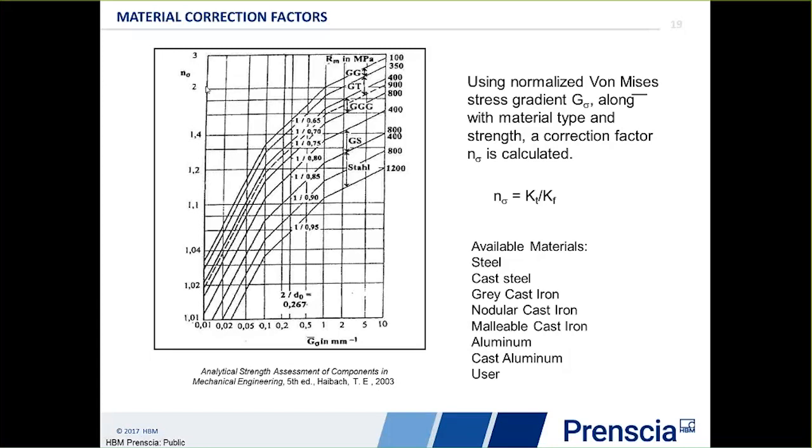And you'll see, especially for gray cast iron, that these corrections are relatively high. So basically, I'm cutting my stress level, in this case, by a factor of 2, that we use for my fatigue calculation. If you go back and think for simple materials on how we estimate fatigue curves off UTS, a very popular methodology says that at UTS, I fail in one cycle, and my fatigue limit, infinite life, is half UTS. So a factor of 2 took me from infinite life to failure at one cycle. So you see the impact of these large reductions in stress on our fatigue curves and why we need to do notch sensitivity calculations with gray iron just to make useful information out of it.